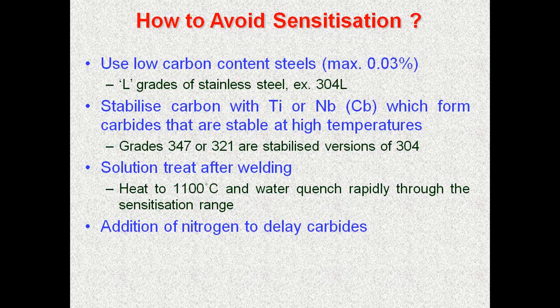Another option is that you have done the welding, you have done the heat treatment, you are having an apprehension that the chromium carbide would have formed and sensitized structure is there. Then you can heat it to a higher temperature, around 1050 to 1100 degrees, and water quench rapidly. Then you will find that the carbides are redissolved as carbon and chromium, and you avoid sensitization. Additionally, one of the options is to add nitrogen, which retards the formation of carbide, and it will not be creating a sensitization problem. Nitrogen up to 0.16%.